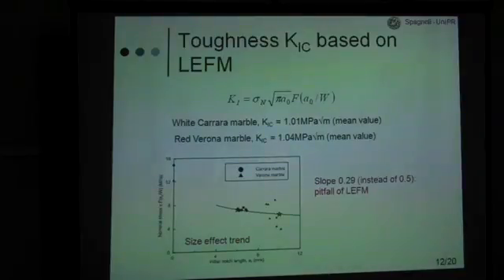So what we start with at first is a calculation of the toughness based on linear elastic fracture mechanics from the initial notch length, and these are the two mean values that we work out for the two materials, and they are pretty close. And we can see clearly that if we represent the data in a plot of a nominal stress adjusted by the relative notch depth versus the initial notch length, the trend of the results is not following linear elastic fracture mechanics, as expected.